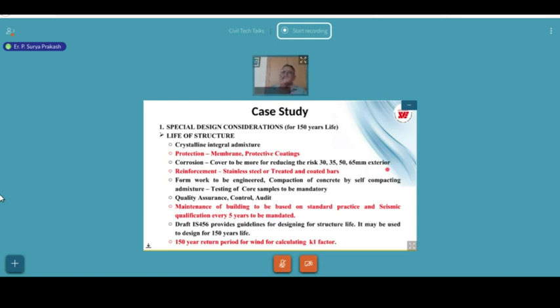That means you have to do the cutting and bending in the factory, and after cutting and bending, you do the coating, or you can even go for galvanizing. And formwork to be engineered formwork, because formwork is the biggest culprit in construction. So if the formwork is not proper, you will have the honeycombs and all in the concrete, which cannot even be thought of. We are talking about porosity, how you can allow honeycomb at all. So the compaction of concrete by self-compacting admixture and testing of core samples to be mandatory.